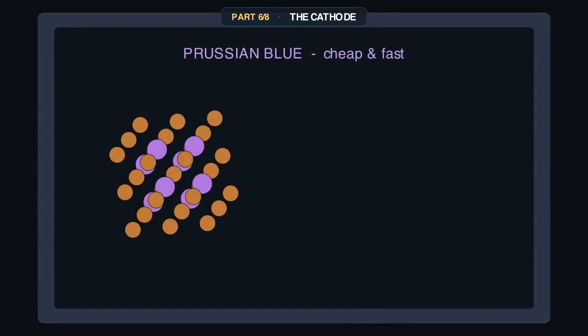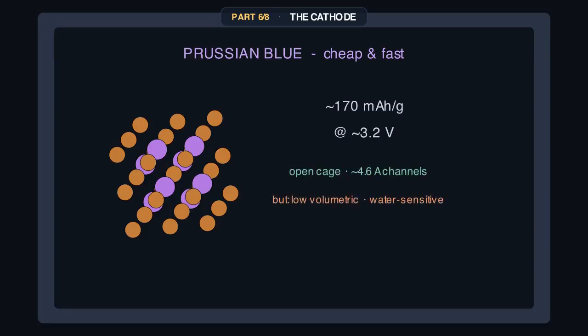Branch 3, Prussian blue analogs, yes, the pigment. An open iron cyanide cage with wide, roughly 4.6 angstrom tunnels sodium rockets through. Fully sodiated, about 170 mAh per gram, near 3.2 volts, dirt cheap and fast. But it packs loosely, so low volumetric energy, and it hoards water and framework vacancies you must bake out. This is a real niche, power and life over density. Honest footnote: Natron bet its whole company on this chemistry, and Natron ceased operations in 2025. The field is brutal. That's every piece.